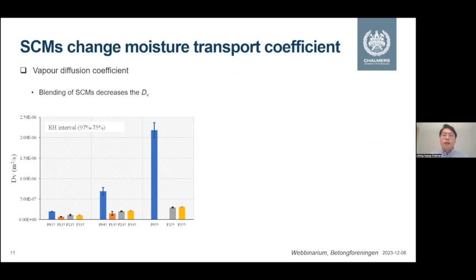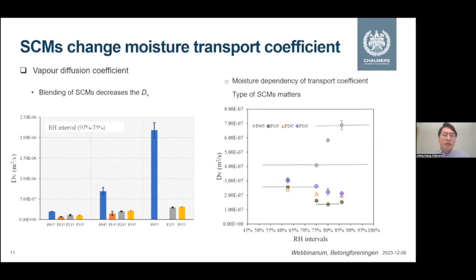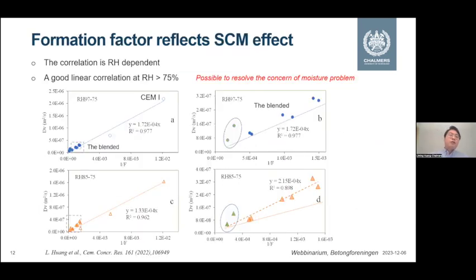And talking about durability, I think there are some concerns about moisture problems induced by use of SCMs. We see here, by measuring the vapor diffusion, that blending of SCMs will decrease the vapor diffusion coefficient. It also changes the moisture dependency of this diffusion coefficient. But if you use the formation factor or electrical properties to describe this effect, it matches well, at least for RH conditions higher than 75%. The correlation between the inverse of formation factor and the vapor diffusion coefficient is more or less linear at high RH intervals.